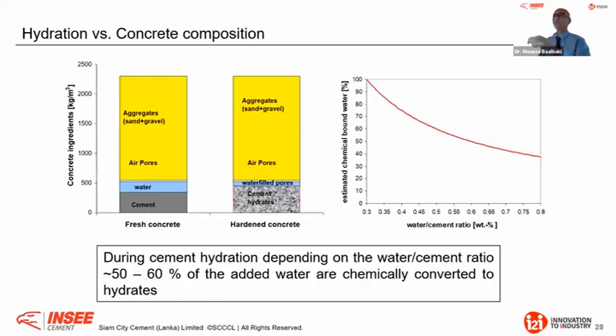After that, we come, for example, to the concrete side. Therefore, you see, from the fresh concrete, you go to hardened concrete. The aggregate sand stays aggregate sand in the microstructure, okay? You have an interfacial zone of transition between the hydrated cement base and the aggregates, okay? Now, you have the water-filled pores, and those water-filled pores will depend very much on the water demand.